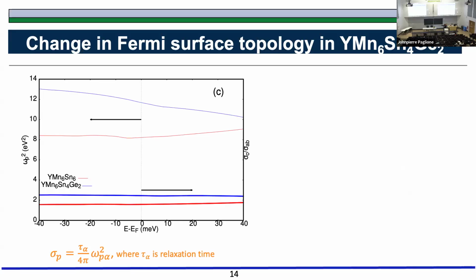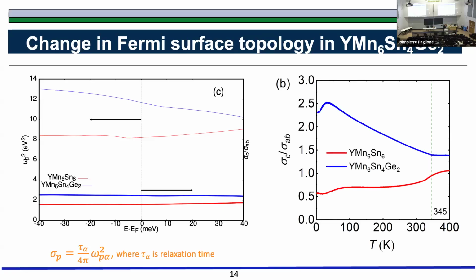So from this calculation of the plasma frequency, we could see that it had changed the anisotropy of the Fermi surface. And this was very consistent with what we got here. You can relate this plasma frequency to the conductivity of the material, and you can calculate this plasma frequency along the C-axis and in the AB plane, and you take a ratio, and these are the plots for the ratio. The blue one is for the germanium compound, and this is for the parent compound. We get a similar state here.